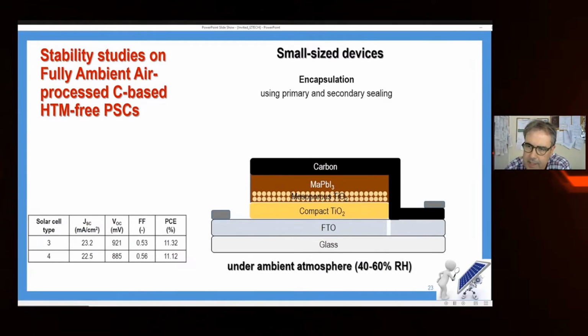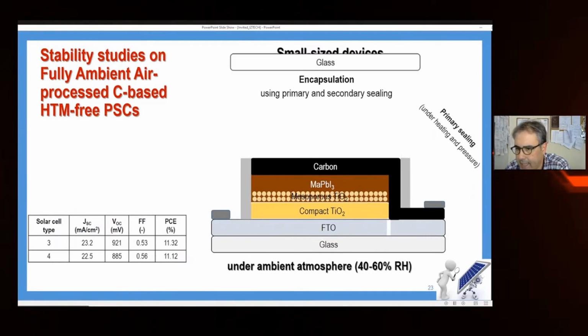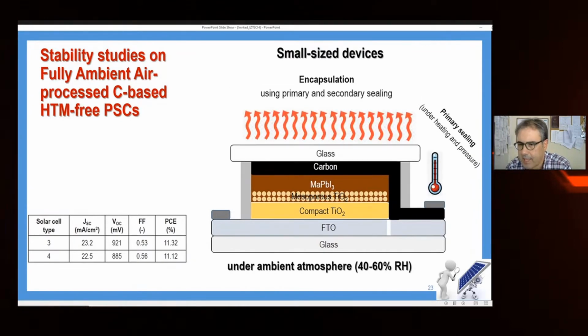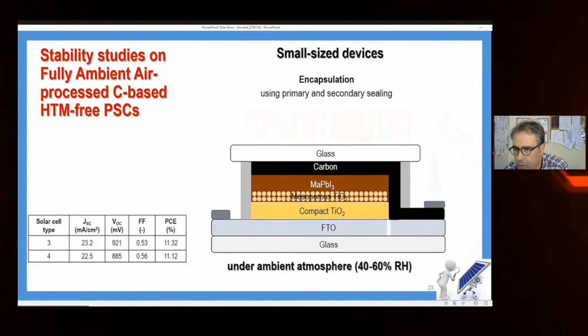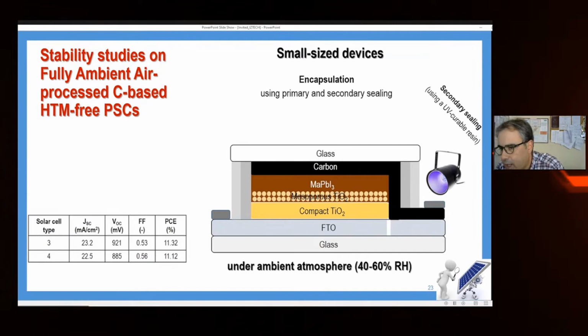As a first primary stage, we put a sealant and a plain glass on the top. It is a thermoplastic material that isolates this structure from the environment. But to be sure that this device would be stable after a long time, we also have a secondary sealing process, which is based on a UV curable resin. We illuminate it with UV light to make it a very hard material at this stage, to be sure that we have a complete isolation of the device from the environment. This is the common procedure that we follow to have stable devices, and of course to expose these materials now to standard tests that are always needed before we go to commercialization.